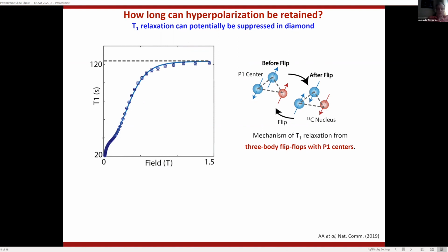Right, but you could measure time-dependent build-up, and if it's seconds or longer, then it's probably spin diffusion, not like the transient flips that you mentioned. I mean, what's your time constant? So the time constant is usually just set by the T1 of the nuclei, and this is about 10 seconds or so, 10, 20 seconds. But why we see this transient is because you can actually pulse the P1 centers. Yeah, you can manipulate them during the process.